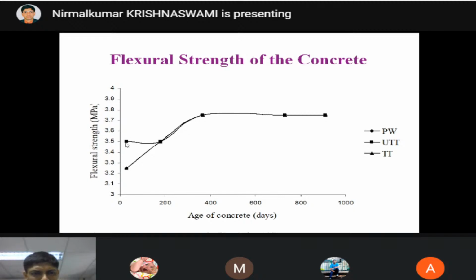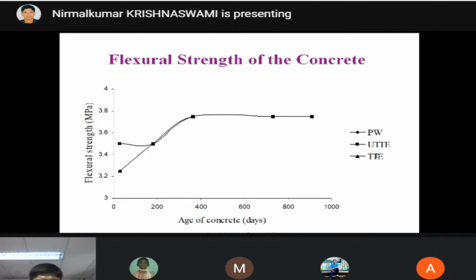It's a minimum of 3.5 flexural strength and the maximum is 3.8 MPa. This is for tannery effluent and this is for textile effluent. So the flexural strength is very, very good. There is no much issue in this flexural strength. All the three strengths, compressive, tensile, flexural, no problems.